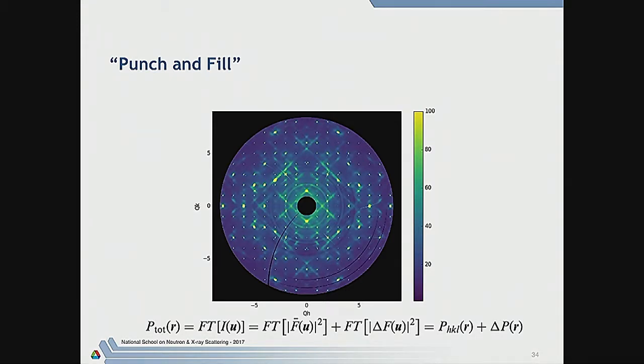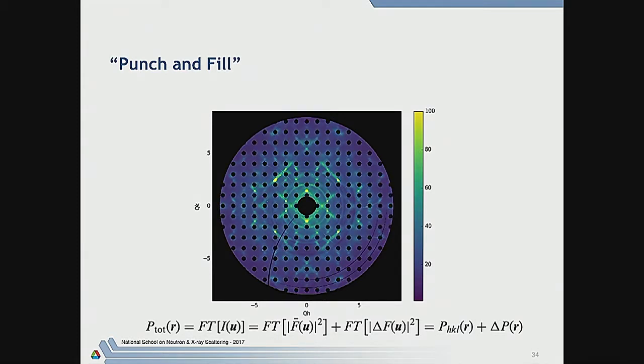So is there a way of perhaps just concentrating on this, because this is what we're really interested in? We can solve crystallographically what this is by just looking at the Bragg peaks and forgetting about the diffuse scattering. But the reason for measuring the diffuse scattering is because we want to determine this. Can we determine this by getting rid of the Bragg peaks? Well, of course, there's a very simple way of doing that, and that's to get rid of them. Okay, it's what the punch method means.